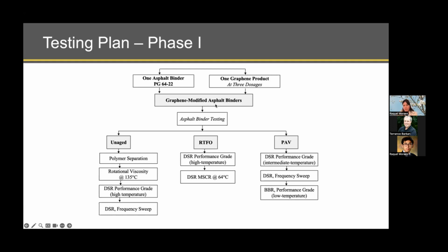Then we perform 2 types of aging, and I'll be discussing this in detail every time that I disclose the results obtained for each of the tests. We have what we call a short-term aging and a long-term aging. So in synthesis, what we evaluated here was the rheological properties of the asphalt binder modified with the graphene additives.